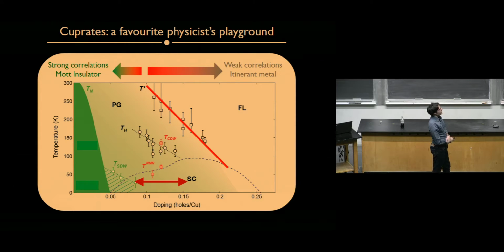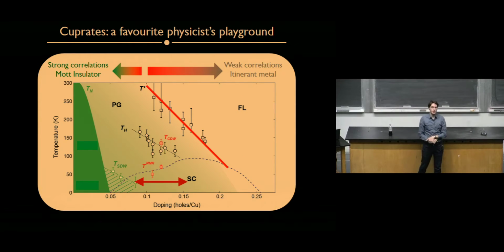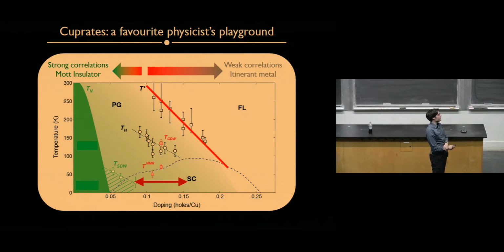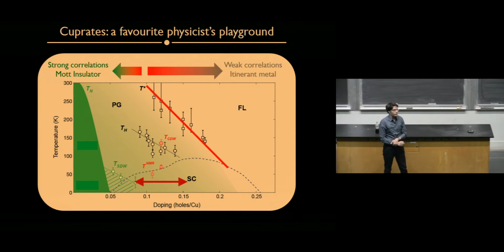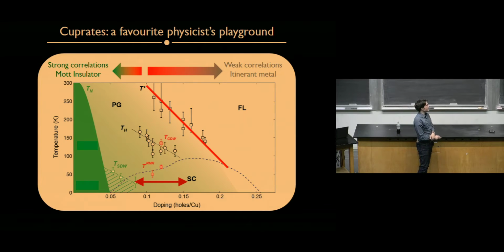And this is the phase diagram of the cuprates. So we have antiferromagnetism here, this green dome is antiferromagnetism. This is Fermi liquid. So here you have an electronic liquid state. So there's no electronic crystal. There's no particular fancy electronic phase here. This is still an interesting state to study, but there's no electronic order down here. This is a superconducting dome, and, sorry, I forgot to mention, this is a function of doping and temperature. Okay, so superconductivity happens at about 5%. This is the case of one particular compound, which is called YBCO, but the shape of the phase diagram is similar for all of them. And then typically the superconducting dome ends around 25% in the so-called overdoped region. So this is the overdoped region, underdoped, and this is optimally doped.